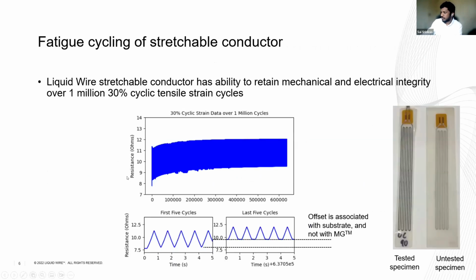On the right side, you see a strain gauge. It's a single trace, but in a multi-loop trace that's connected to a PI board on the top, and this structure is made out of TPU. We have stretched the substrate over 1 million cycles. The entire test took 7 days to complete. When we finished the test, you can see the graph. The base resistance has shifted a bit, but still the signal integrity remained really, really good.